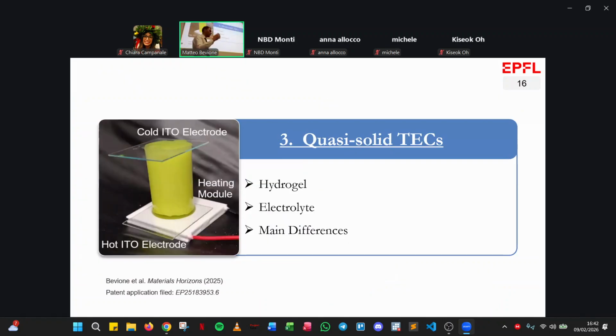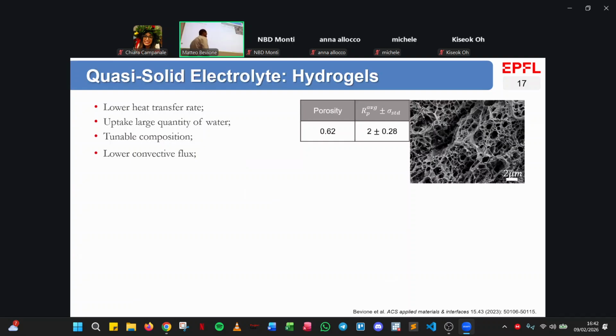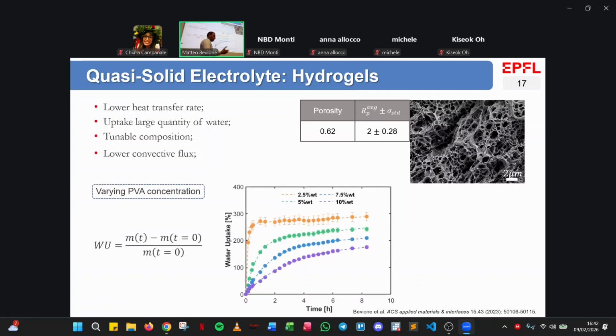So here is where it comes into play my second love of the PhD, which are the hydrogels. And the thermoelectrochemical cells can be quasi-solid, apparently. So I relied on the use of these nice materials. Hydrogels are just basically polymeric sponge. You can develop a hydrogel starting from a monomer, and then these materials will have the nice properties of uptaking a large quantity of liquid, and as you can see in this graph, they fundamentally become the electrolyte themselves. So you will take them, put them in the electrolyte solution, and voila, there you have it.